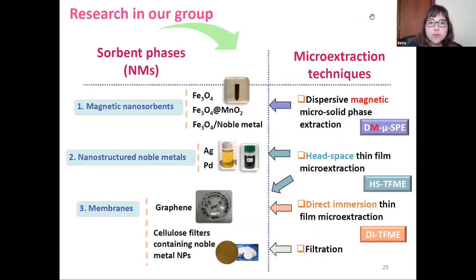In our research group, we use mainly three types of sorbents, as we can see here. First, magnetic nanosorbents, including magnetite, magnetite modified with manganese oxide, and magnetite in the presence of noble metals. Second, nanostructured noble metals of silver and palladium, and third, membranes of graphene and cellulose filters containing noble metal nanoparticles. We tested several nanoparticles of silver, palladium, and gold, but this application is with silver.